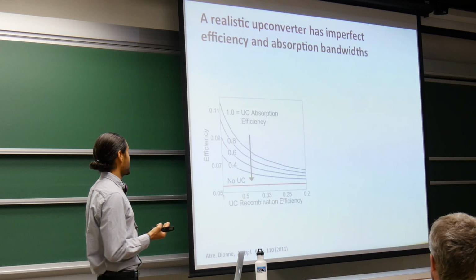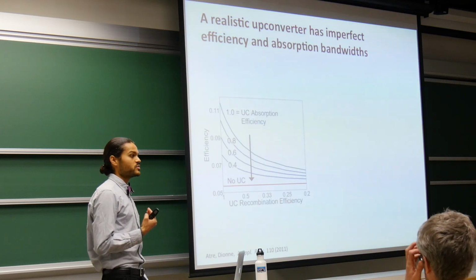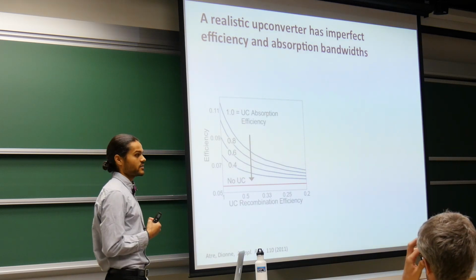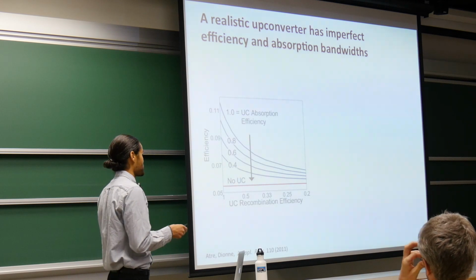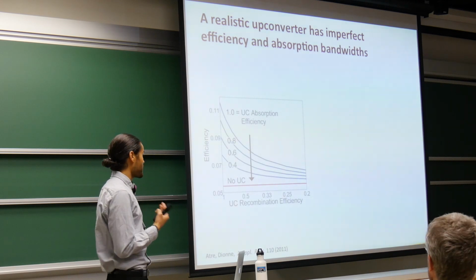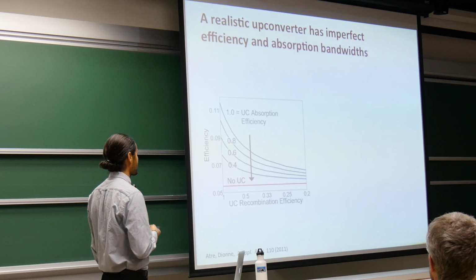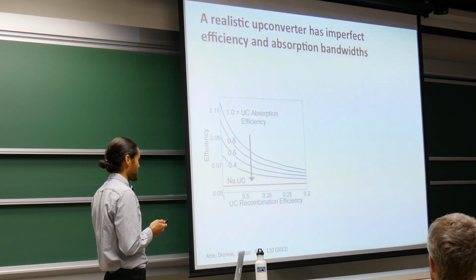As we expect, if we decrease the amount of light that can be absorbed by the solar cell, the efficiency of the combined device decreases. And as we introduce more non-radiative recombination events into the process, the efficiency decreases as well.